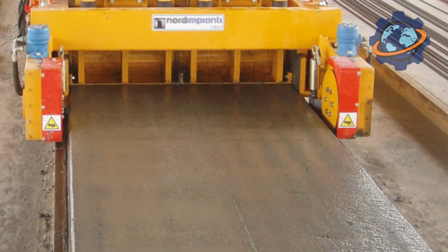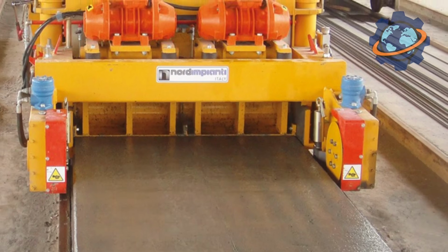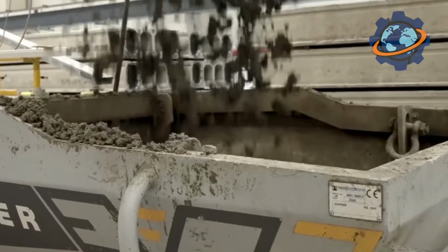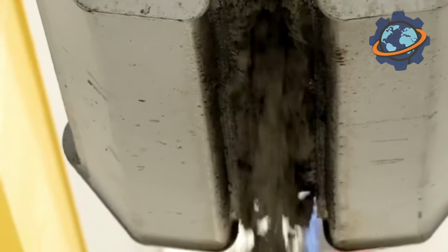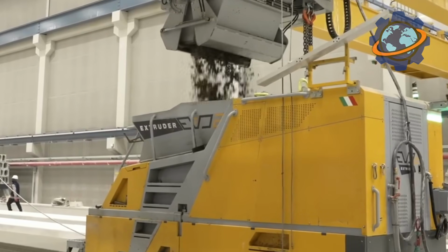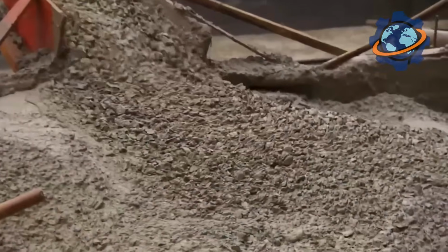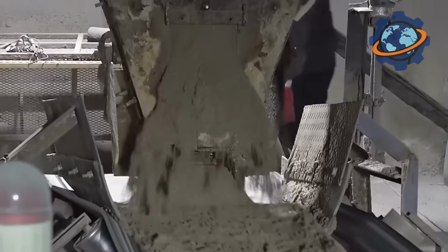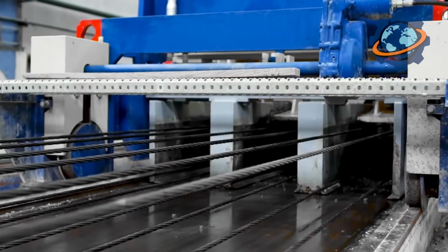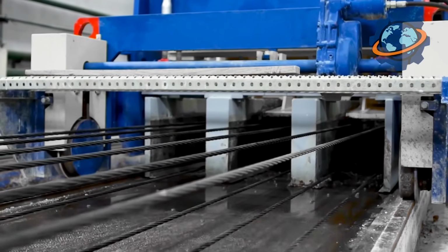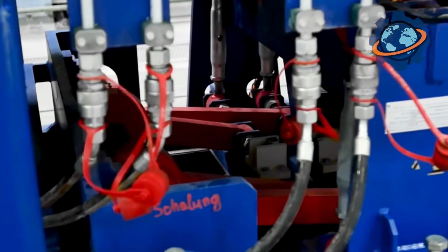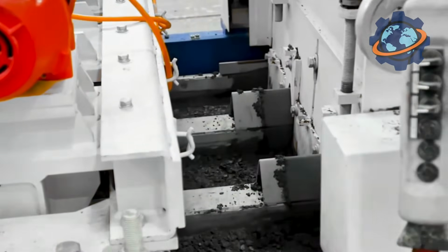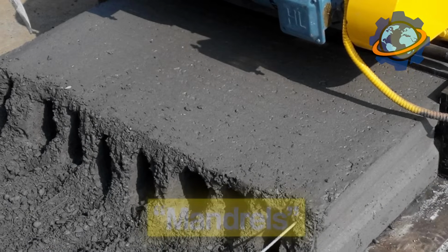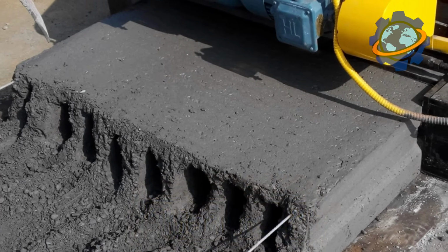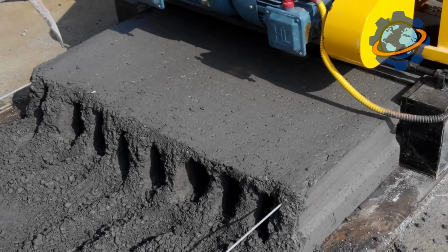And so, this machine begins its slow journey. Inside, a real marvel takes place. Firstly, the concrete from the hopper is fed downwards, enveloping our tensioned steel strands. Secondly, special vibrators and compactors ram this dry mix with incredible force, making it unbelievably dense. And thirdly, and most importantly, inside the machine are special forming tubes, or mandrels, which vibrate as they push through the concrete, leaving behind perfectly round, smooth voids.